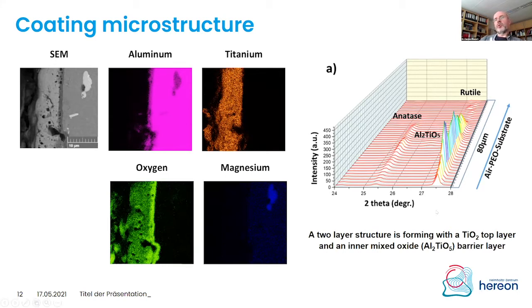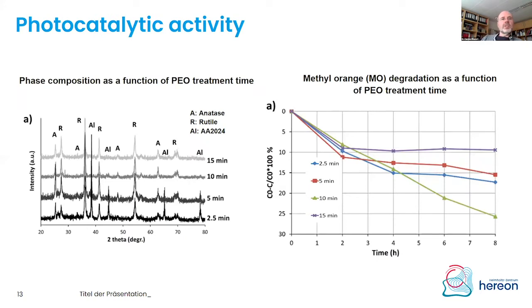And we have also done line scans, following different depths of the phases, coming from the surface of the coating going down to the substrate. And we were looking at the anatase and the rutile peak. This you see in this part, about 80 micrometers in depth. We were following the distribution of those two peaks. And you can also see in the diffraction patterns that there is an interface layer related to the aluminium titanium oxide Al2TiO5 phase, the mixed oxide.